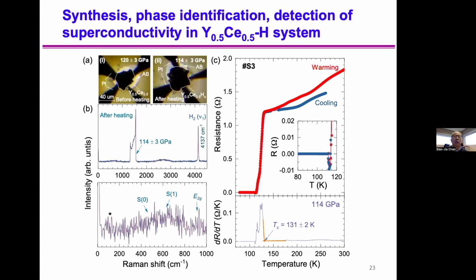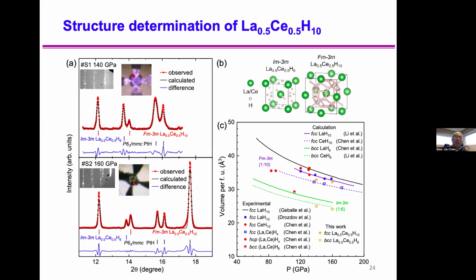For another sample, we synthesize material in the same procedure. You can see we mark the star in figure B, though not showing so clear. The resistivity measurement shows a transition at 131 Kelvin. We use X-ray diffraction to determine the phase. The X-ray gives peaks that belong to a space group like Fm-3m, a cubic phase for our lanthanum cerium H10.